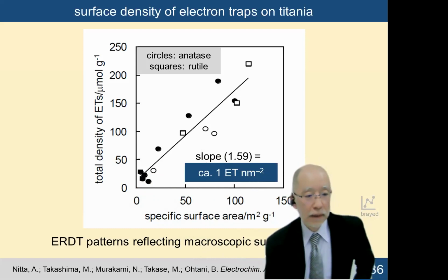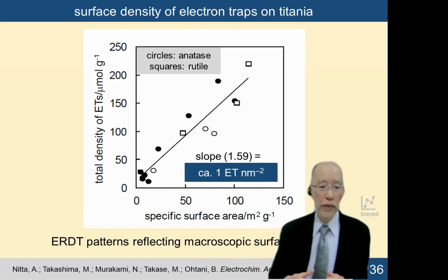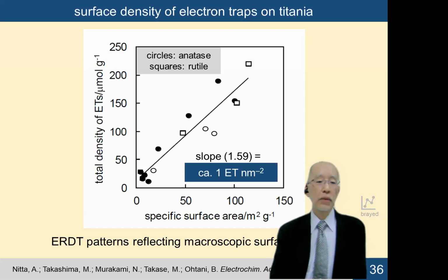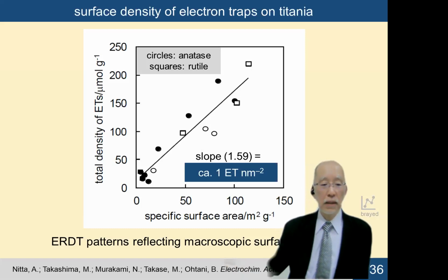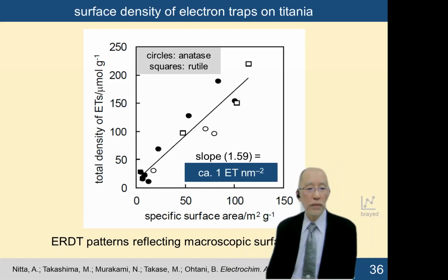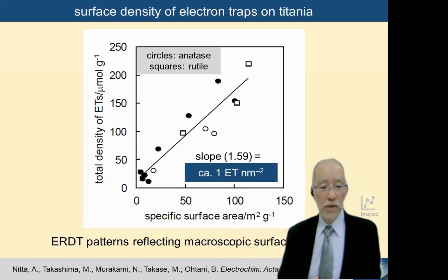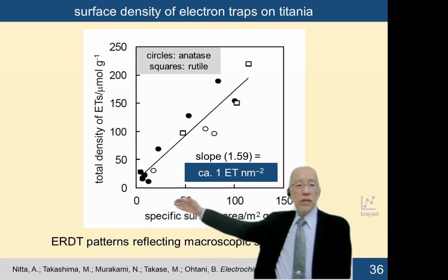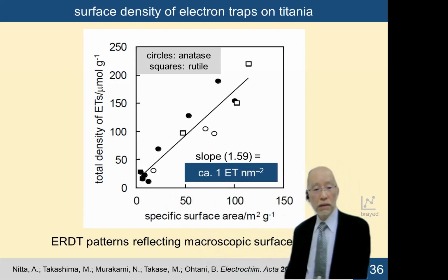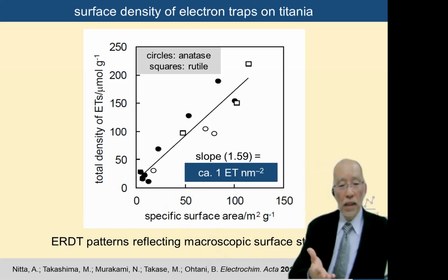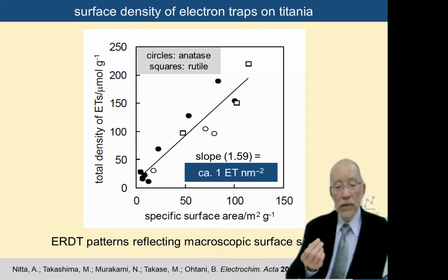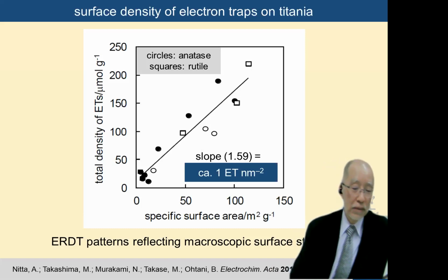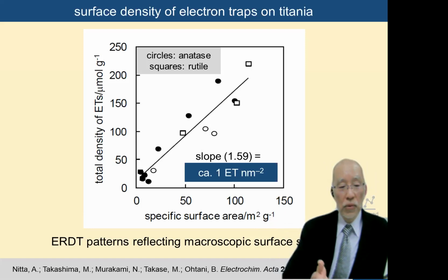Please remind us that surface hydroxyl groups, OH groups on ordinary titanium oxide, have a surface density of about 2 or 3 hydroxyls per square nanometer. And this number, about 1 electron trap per square nanometer, is not so different from those surface hydroxyl groups. And the important point is, if this is almost linearly changing depending on specific surface area, that means those electron traps are only located on the surface, or this technique only measures the surface electron trap. Even if the bulk electron traps are there, it is impossible to measure. But we cannot determine which is the truth. But anyway, only the surface electron traps are measured.